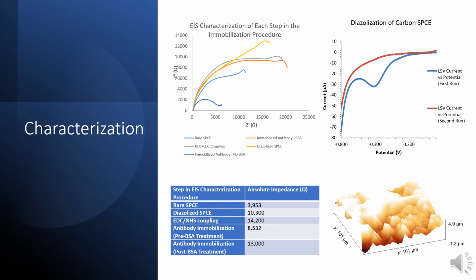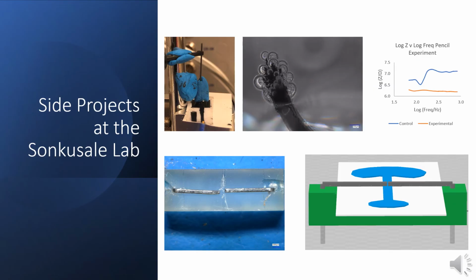These results are promising but still need to be further optimized to prove that the immobilization procedure is following the proper protocol and methodology. One step that I have been working on to better improve the results is to deliver a more smooth working electrode. The figure in the bottom right is an atomic force microscopy 3D image of a small sample of a working electrode surface. The 6 micron deviation in carbon paste is consistent across other electrodes, and hopefully I can reduce this number moving forward.